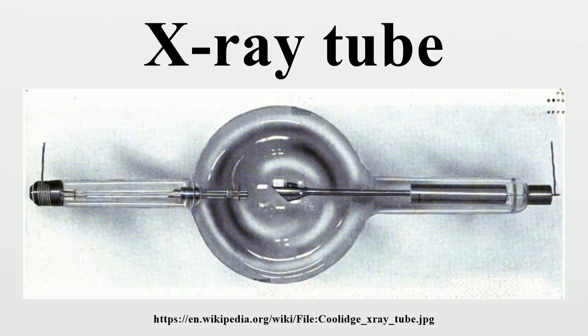Eventually, the tungsten deposit may become sufficiently conductive that at high enough voltages, arcing occurs. The arc will jump from the cathode to the tungsten deposit, and then to the anode. This arcing causes an effect called crazing on the interior glass of the X-ray window. As time goes on, the tube becomes unstable even at lower voltages, and must be replaced. At this point, the tube assembly is removed from the X-ray system, and replaced with a new tube assembly. The old tube assembly is shipped to a company that reloads it with a new X-ray tube.